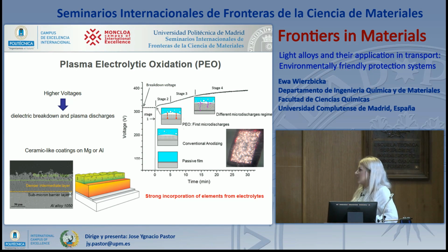The second type of anodic coatings are coatings obtained by the plasma electrolytic oxidation process, which requires very high voltages. The beginning of the process goes through the same stages as classic conventional anodizing. Firstly, a passive film is formed, then a porous structure, but after exceeding some breakdown voltage, microdischarge and plasma formation start. What can be observed on the metal surface is the formation of small sparks.